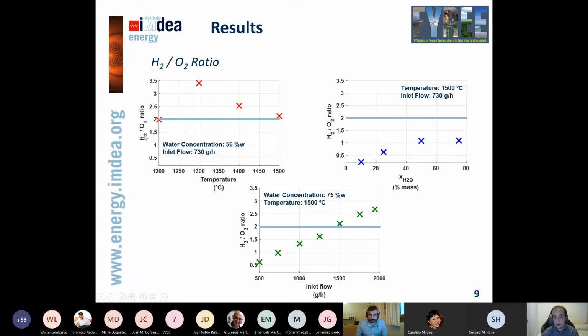Here in this case, we're just producing more hydrogen than expected. So basically, we are covering some extra vacancies that were reached before. While in this plot here, when we consider water concentration, it is the other way around. We are generating more vacancies than those that we are covering, that we are using to produce hydrogen. And something quite peculiar happens with the flow, in which we go through this line from a place in which we generate those vacancies to another place in which we consume them.